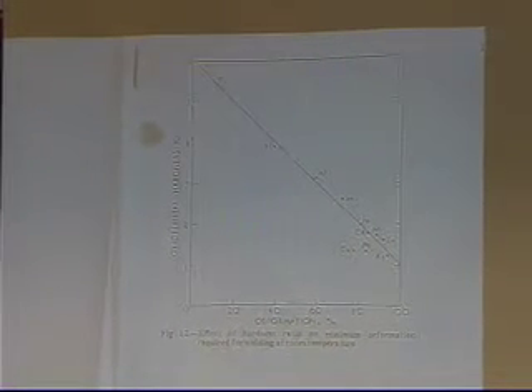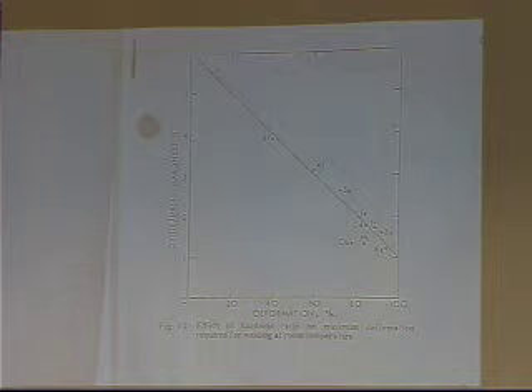The big difference here is this is relatively pure aluminum. This is a higher strength aluminum alloy. And you have a big difference in how much deformation you have to have. Tin is in here. Tin's oxide is relatively smearable. It's like butter, okay, peanut butter. Spreads over the surface. Copper's even worse. Copper's got an oxide that smears over, like soft butter. Here's lead, iron, nickel. Most things take 80 to 90% creation of new surface in order to get a decent bond, because those oxides tend to spread out and smear over the surface.